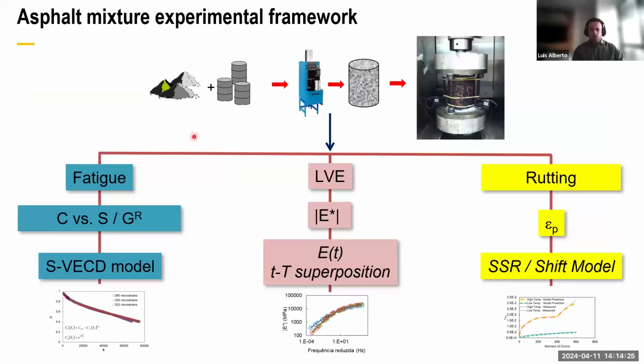Here is the asphalt material experimental framework. It's well-known testing, even though we have some specific procedures for Brazilian materials. I think you are used to this kind of testing. For fatigue, we use the S-VECD model. For linear viscoelastic characterization, the dynamic modulus test. And for rutting, the stress sweep rutting test coupled to the shift model for predicting rutting. So this is our experimental framework.